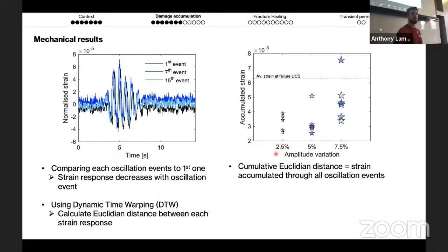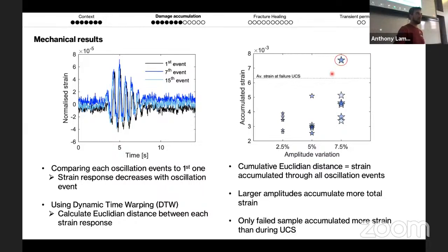Okay, so here is the small amplitude oscillation test for all the samples, and then the large amplitudes for all the tests. What we see is that there is a general trend that the larger the amplitude, or the larger the oscillations introduced, the more strain will accumulate. What's quite interesting is that during one of my tests, one of the samples failed mechanically. And that was the only sample that also accumulated more strain than the average strain at failure during the UCS test.